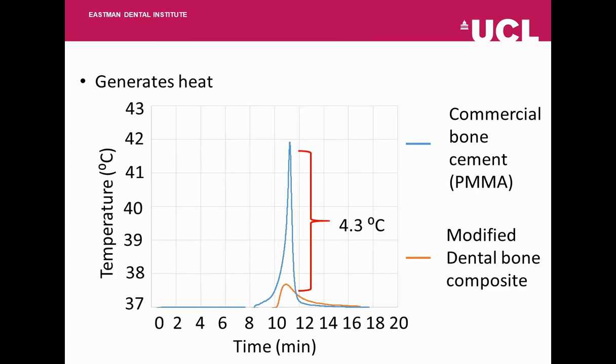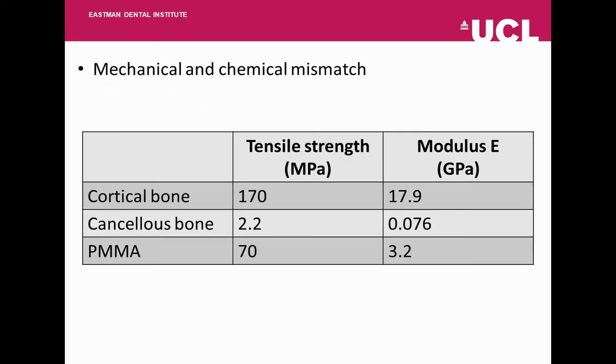Now, the amount of heat generated, if you want to calculate it, is the area under the curve, and larger volumes of the material will inevitably generate more heat. Here, only 0.47 grams of material was used, and normally in a clinical setting, approximately 10 grams are used, so a lot more.